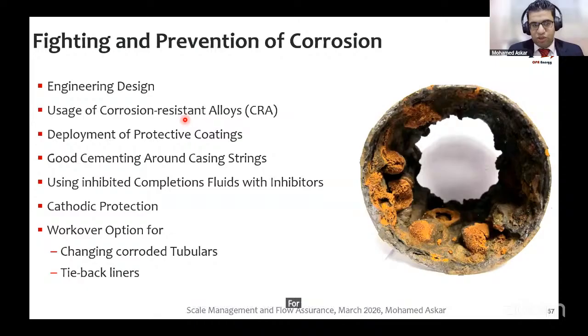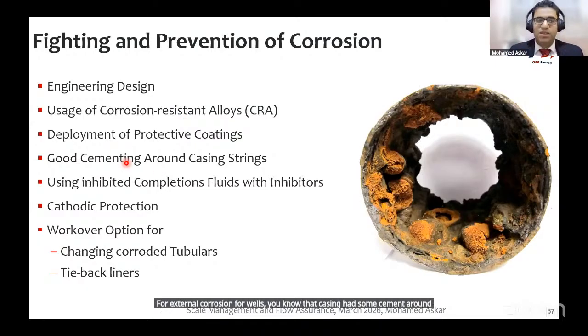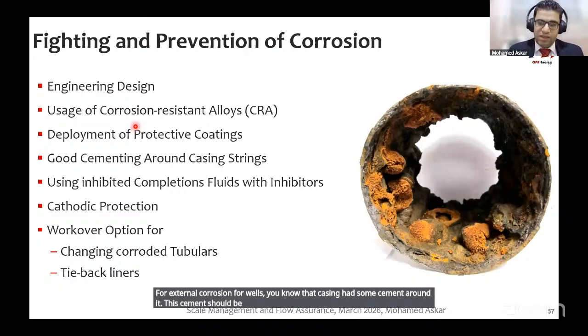For external corrosion, for wells, you know that the casing has some cement around it. This cement should bond well to the casing and cover the casing from all directions to prevent interaction between the aquifer water and the casing itself, which would cause outside corrosion.